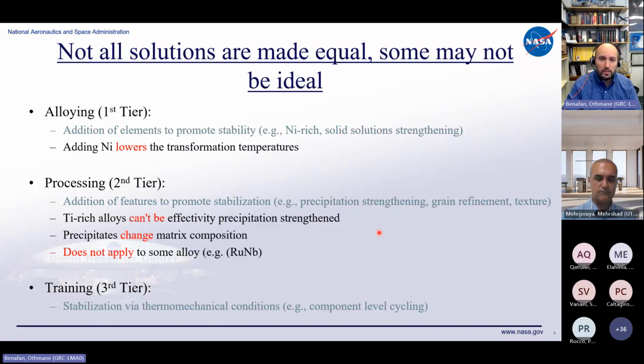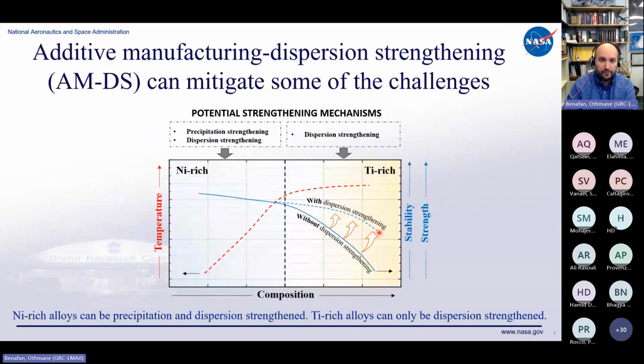So here we introduce the notion of additive manufacturing dispersion strengthening. And the idea here, and just in this cartoon, shows that when you have nickel-rich alloys, for the case of nickel titanium, just as an example, you can do precipitation strengthening, and you can do dispersion strengthening. Okay, and this is what it looks like.